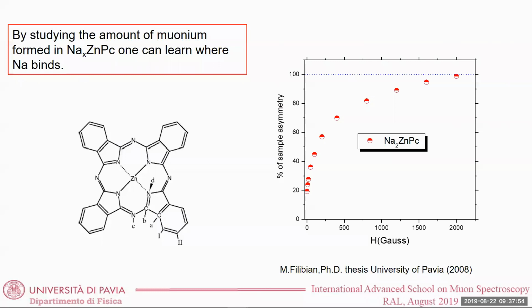What happens is that if we put sodium inside the system, this fraction of muonium dramatically decreases. And this is telling us that what is basically happening is that the sodium is getting attached to one of these sites where the mu plus was getting attached to form muonium. And so we can have an idea where the sodium is going to be placed in the system.